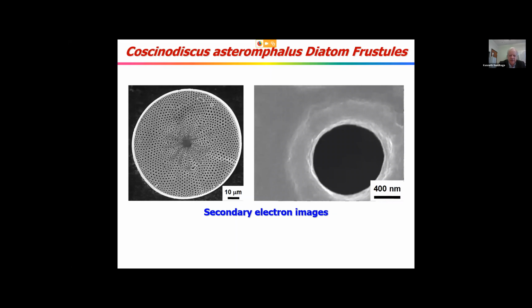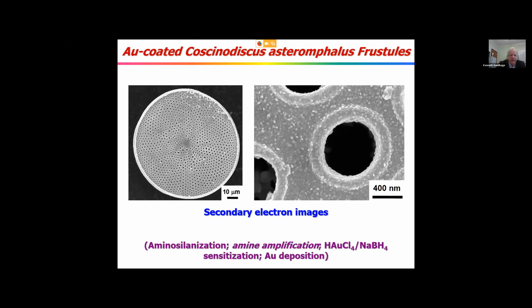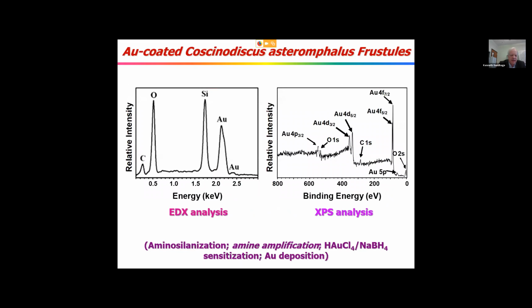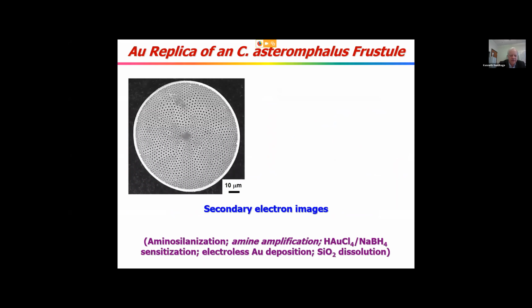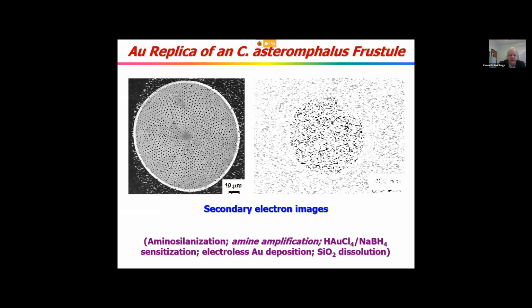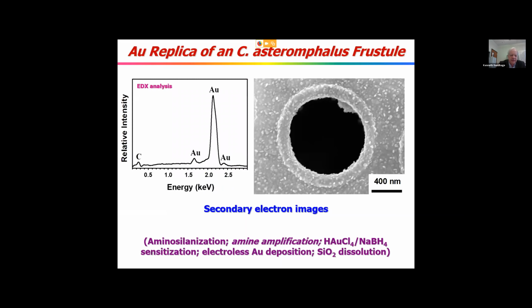This particular diatom frustule has pores that are about a micron or so in diameter. And so we made a gold replica. This is actually a gold-coated sample the same way. You can see on the left the EDX pattern showing silica as well as the gold coating, and the X-ray photoelectron spectroscopy analysis, which is the surface that shows the gold present. We then dissolved the silica through occasional pinholes in the coating. This is an all-gold replica of the starting frustule. Now there's no more silica left from EDX analysis.